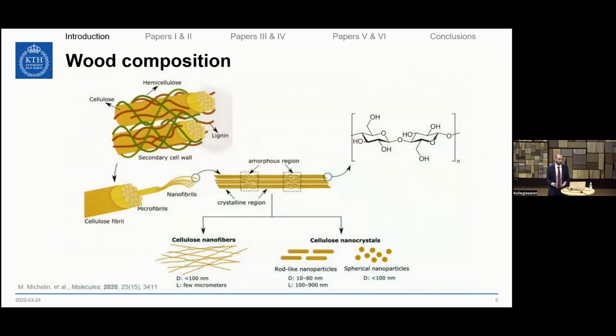Wood is a natural biocomposite where we have cellulose fibrils reinforcing a matrix comprised of hemicellulose and lignin. And these cellulose fibrils are comprised of cellobiose repeating units, which are characterized by less ordered and ordered regions. Upon mechanical and chemical treatments, they either loosen up, so we can obtain cellulose nanofibers or CNFs, or we break down these amorphous and less ordered regions, so we can obtain cellulose nanocrystals.